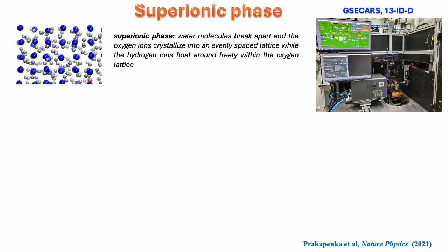Due to limited time, I will show you only one scientific example, and it's about superionic ice. It characterizes a quite unique state of matter. In the superionic state, water molecules break apart and the oxygen ions crystallize in a lattice that is solid, but the hydrogen ions float around freely within the oxygen lattice. So it's quite an interesting phase, and was not easy to handle at the beamline. Even these days, there are very controversial results on this phase.